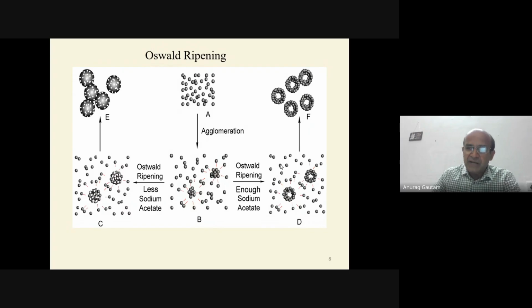So let's say we produce a 20 nanometer particle during synthesis, and we are adding seeds of the same particle at 10 nanometers. They will just form on the surface and will be consumed by the bigger particle. It is the same way that under a big tree, a small tree cannot grow. They take the energy from there. All small particles have high energy, they will transfer it, and the bigger particle keeps growing.